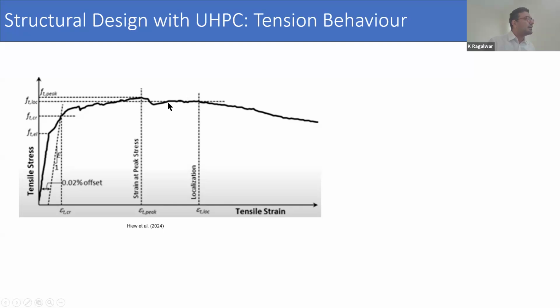So that's why we did not define localization here, because as the crack opens up, another crack formed, and then it helped the stress reach higher with increasing strain. But from this point onward, it never regains any strength or any stress level. It just continuously keeps dropping. So this is the point where we define localization.